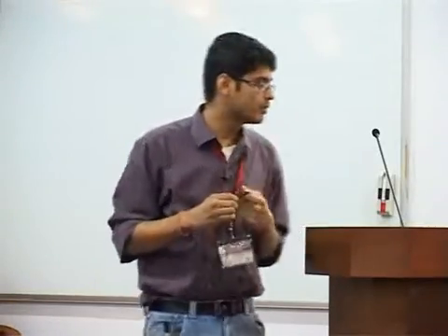For example, this problem was studied way back by Coulomb. What Coulomb figured out was that if I had the old wooden duster, I put it up here, and I measure the coefficient of static friction. We have learnt in our textbooks that the coefficient of static friction is a number which does not depend on almost anything, and certainly not on time. So he said that if I measure this coefficient with this wood having made contact with this wood for, say, 1 hour, I would get one value. If the two woods made contact for 2 hours, the value would be different. And he found that the coefficient of static friction depended logarithmically on the amount of contact time.